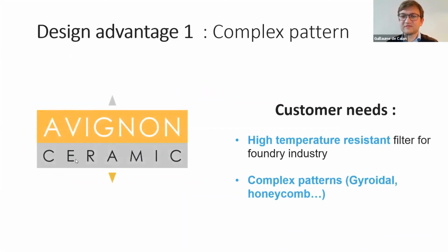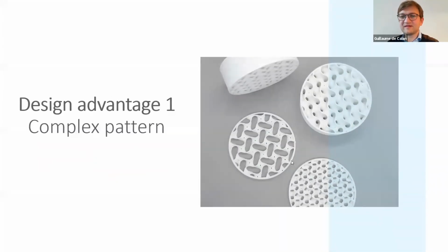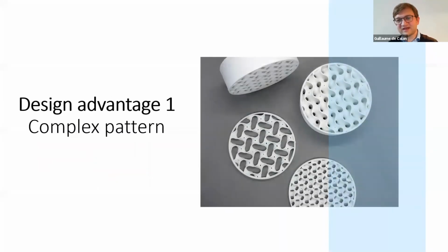In terms of size, that's the interest, we could adapt the mesh size. Here you see a few different ones with different sizes. The block itself must measure something like 6 or 7 centimeters. But we did mesh down to something like 0.4 millimeter up to a few millimeters, sorry, in hole size, depending on the parameters.